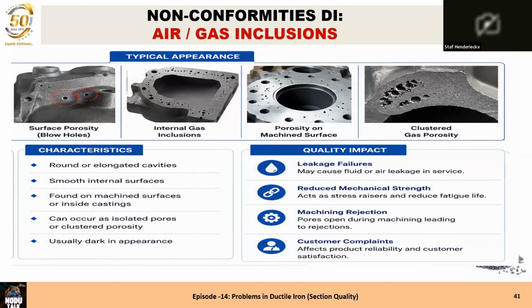It's round and elongated, with a smooth internal wall. It's mostly found on a machined surface, as well on the top as inside when there is a core involved. It can occur as isolated pores or a clustered porosity, and it's usually dark in appearance. Shrinkage porosity, really shrinkage porosity, is not dark, but this with gas and air is mostly a dark one. The problems you can have are, of course, leakage, reduced mechanical strength, machining problems, and definitely your customer will not be happy.